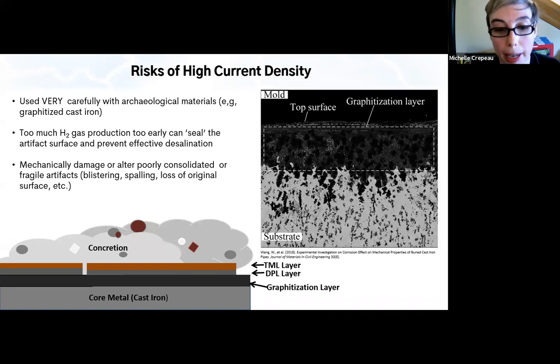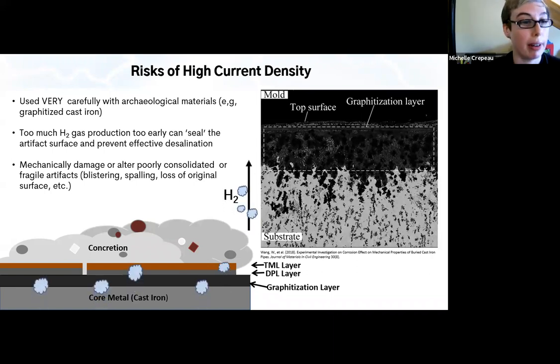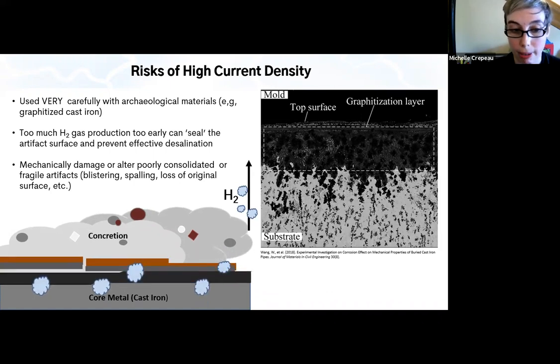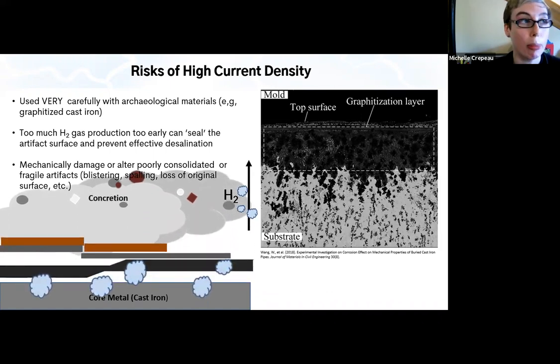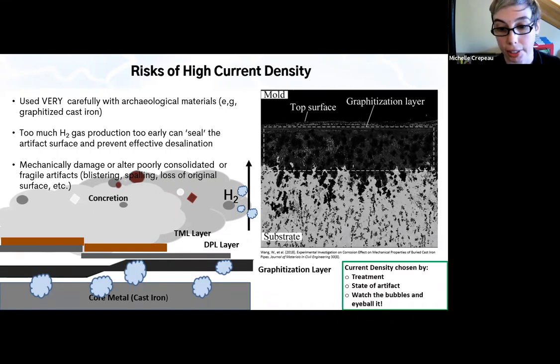And the problem is sometimes this graphite layer is not very well adhered. So when you start producing a lot of hydrogen gas and this expansion process happens, not only will you be removing your concretion and your other layers of corrosion and things you don't want, you also risk losing that surface of the artifact itself and actually breaking or damaging your artifact through blistering or spalling. So that is the major risk of high current density and one of the reasons it is used very judiciously.